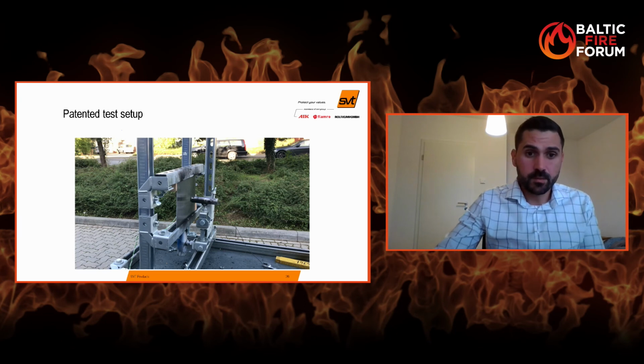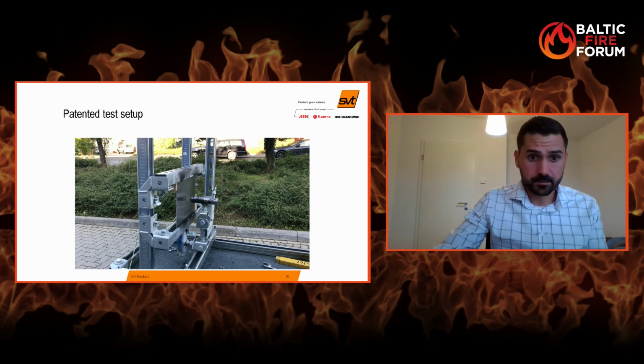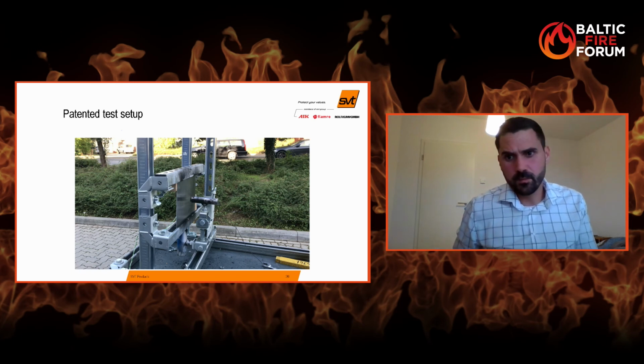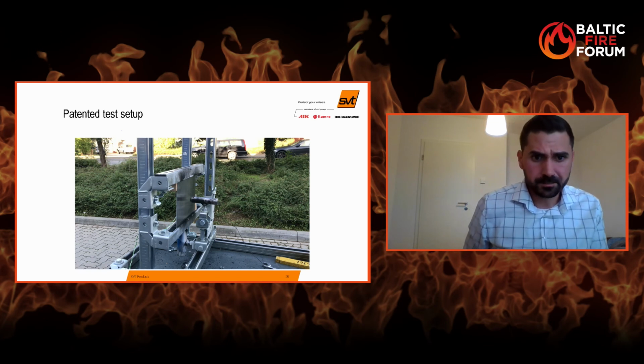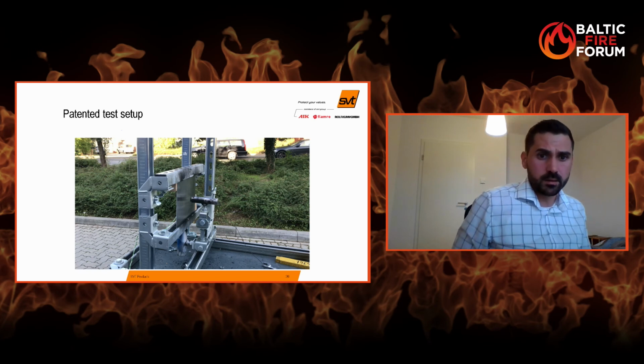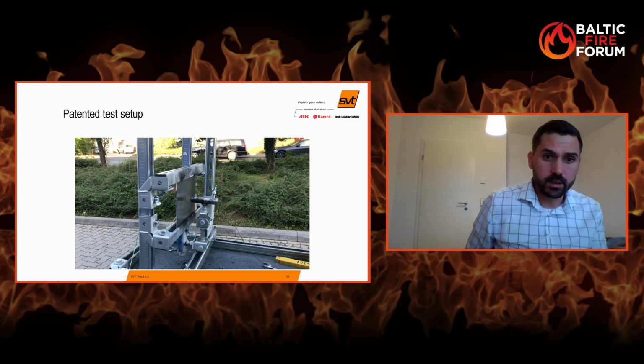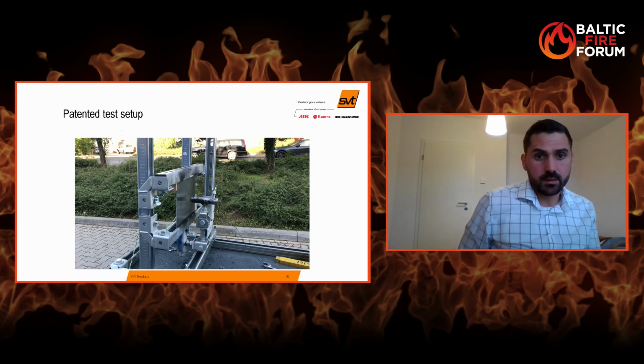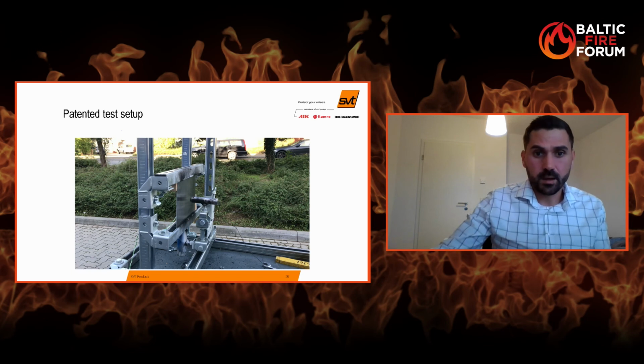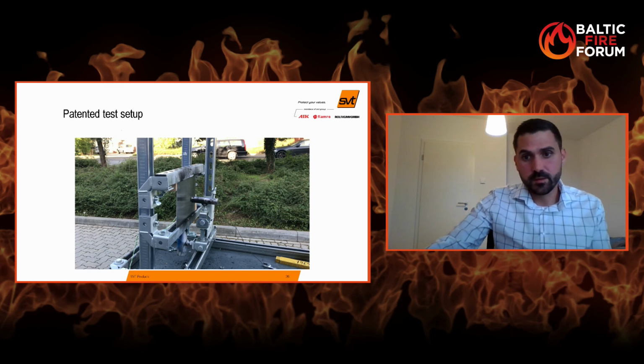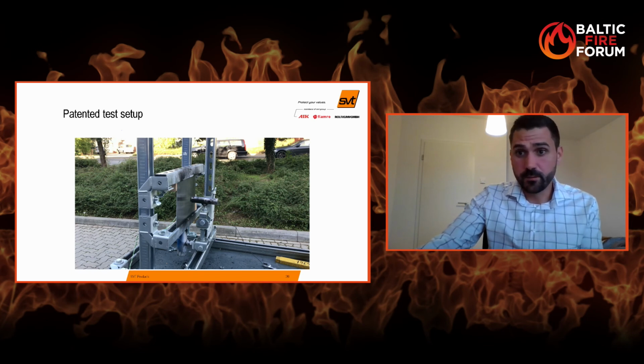Here's a picture of this kind of test setup, which is already patented by us. As you can see, here is the substrate. It's an aluminum plate, I guess, or a steel plate. You have 20 millimeters from the substrate to the reaction material, and you can see it's very simple, but it's very effective.